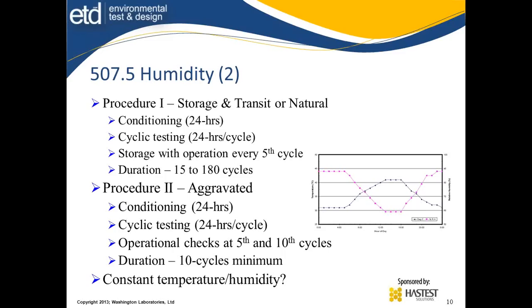Cyclic testing again with 24 hours per cycle, and checks at the 5th and 10th cycle with a 10-cycle minimum. Basically, we've increased the exposure rate, the depth of the humidity or the temperature. This could produce for a constant humidity or temperature humidity. That is quite frankly called out more frequently on a tailoring process than most others. So when the time gets shortened, they take care of that.